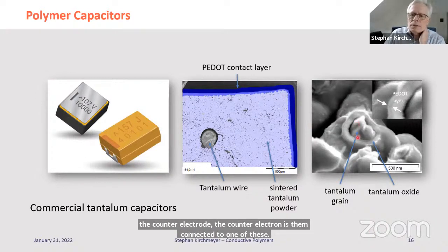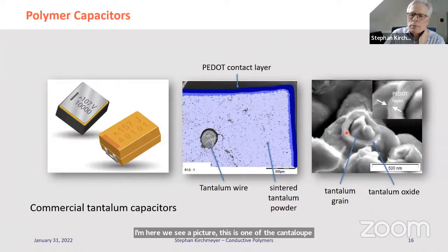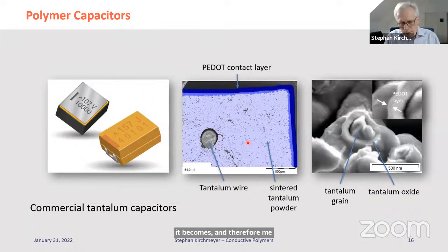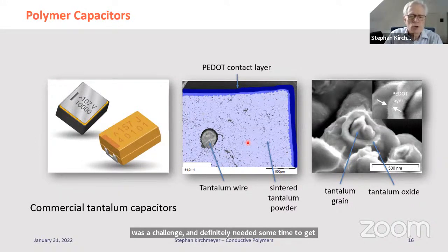Here we see a picture. This is one of the tantalum grains. It is surrounded by tantalum oxide. And if we look, the PEDOT layer is a very small layer which has been impregnated on top of this powder. You could imagine that impregnating here at this point is still very simple, but the deeper we go into the capacitor, the more problematic it becomes. And therefore, making a capacitor using the full capacity of this powder on the one hand, and on the other hand, leveraging the high conductivity of the PEDOT, was a challenge and definitely needed some time to get to a suitable process. So first of all, it was done by impregnating the EDOT, the monomer, and then polymerizing the EDOT inside this structure.